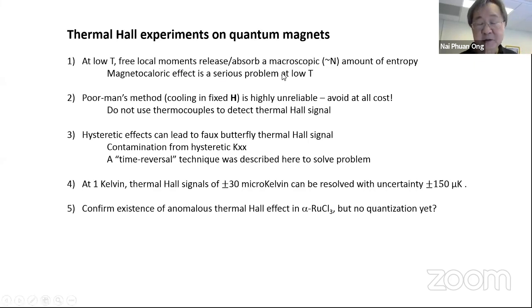So this amount of entropy comes out or is absorbed whenever you change the magnetic field or you change the temperature. It's pure thermodynamics. You cannot escape it. And it's a serious concern for all thermal Hall measurements. So if you adopt the poor man's method, which several groups have done to our dismay, the poor man's method is you hold the field fixed at, let's say, 7 Tesla and cool the sample from room temperature down to 3 Kelvin or whatever, and then take the Hall signal, warm it back up, reverse the field, and then cool it down again, and then you subtract.